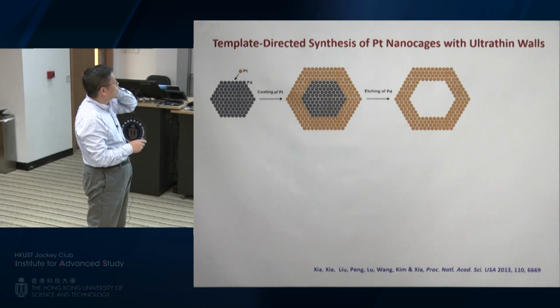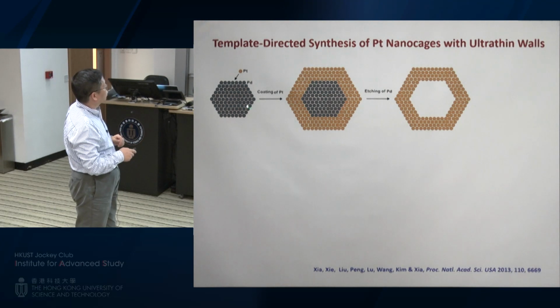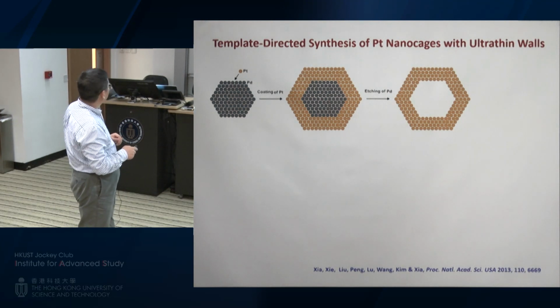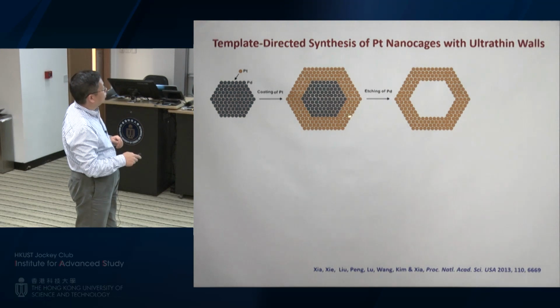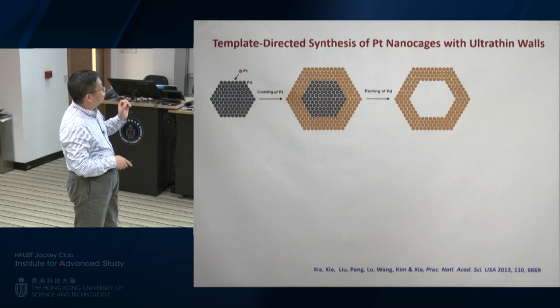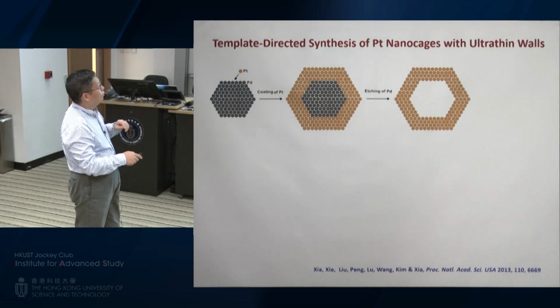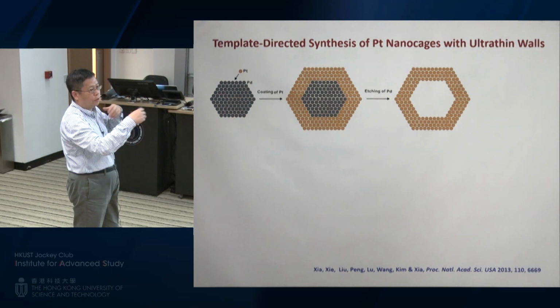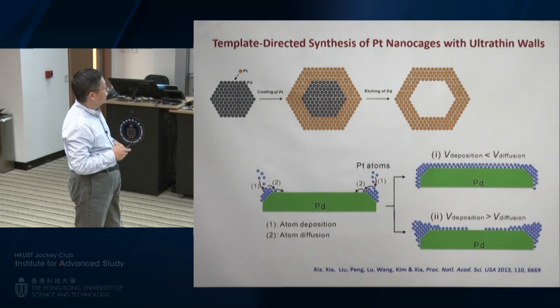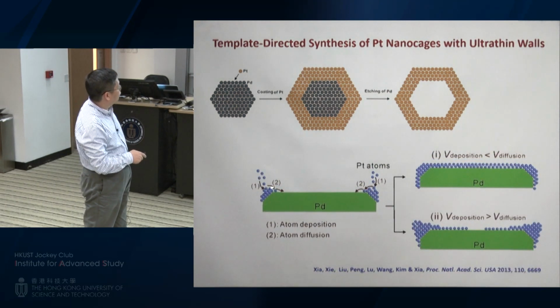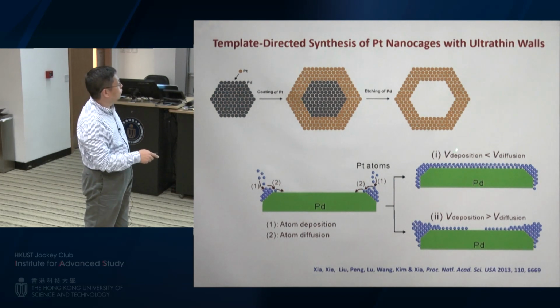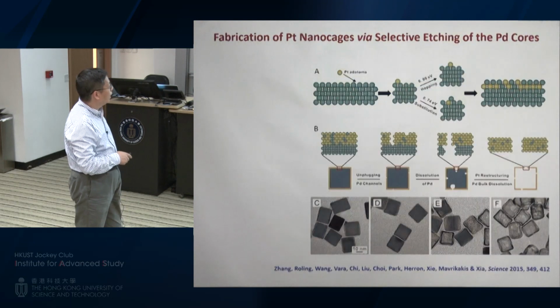And here is the approach I already showed you earlier. You can make these core-shell structures by starting with palladium and coating with platinum, only a few atomic layers, then etch away the palladium. The key point over here is you have to make sure you can make a conformal coating. Otherwise, you're going to change the facet on the surface. This is already very clear from the previous discussion. You have to make sure diffusion is going to be able to overcome the deposition rate so they can have a conformal deposition. Otherwise, they may form islands on the surface, right?